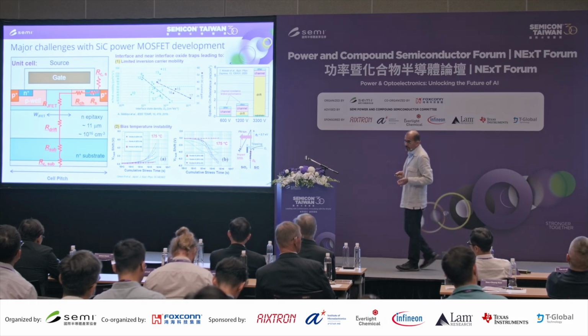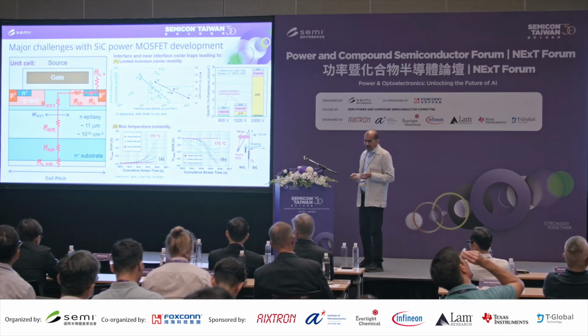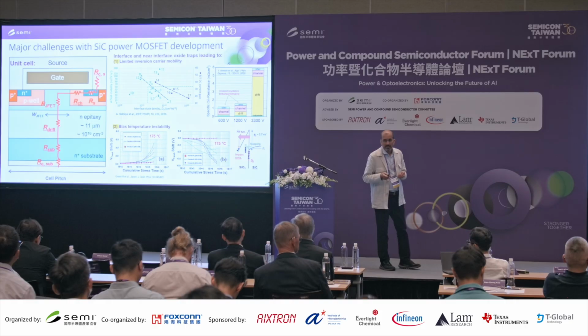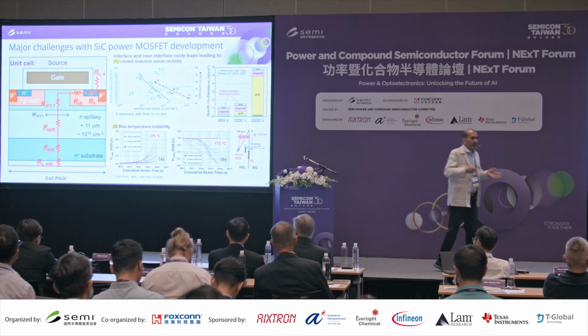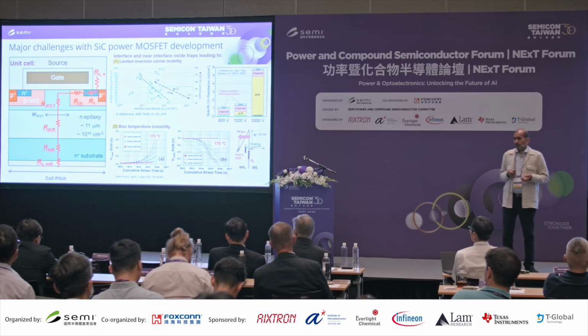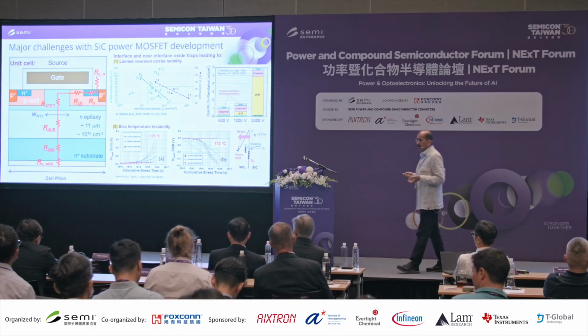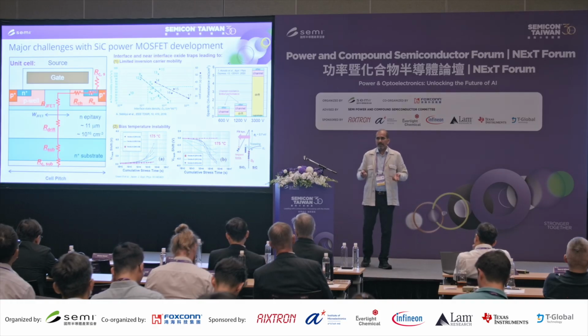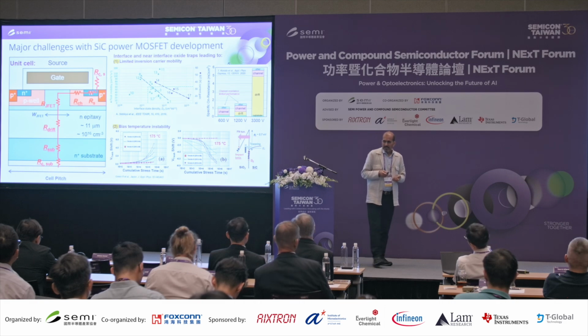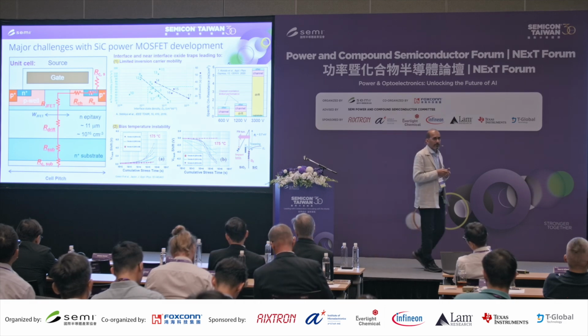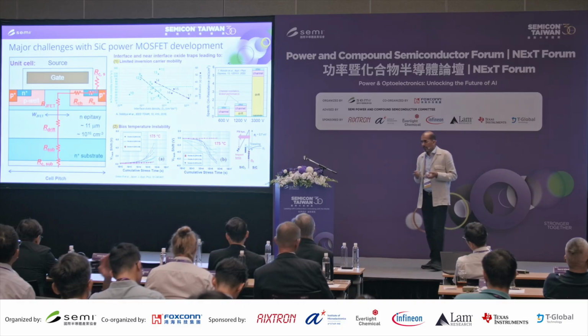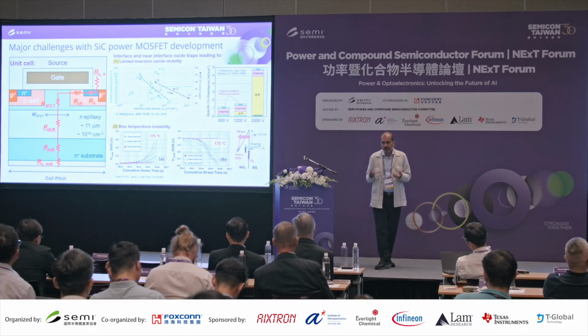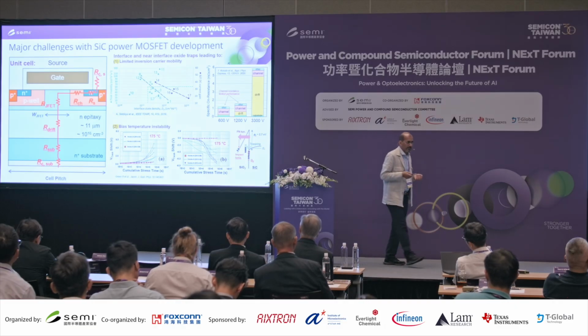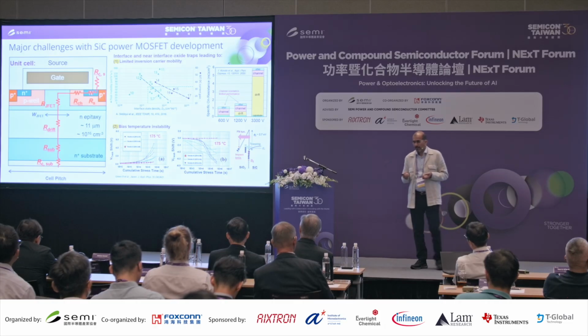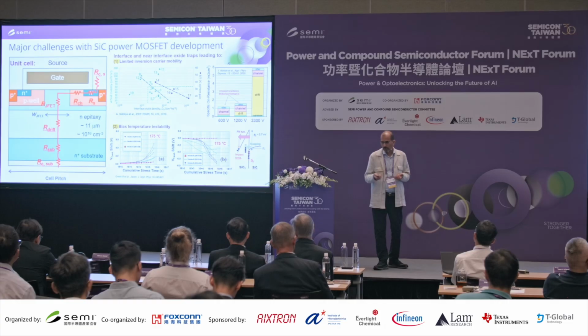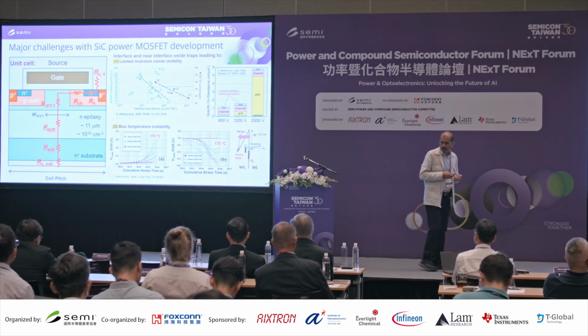So that means it requires a lot of engineering. Because of that, you can see in the right side figure the channel resistance, especially for low voltage devices, and when I say low here, it is up to 1200 volt, which is for EVs. For up to 1200 volt devices, the channel resistance is a significant part of the total resistance, and one needs to really improve that to have highly efficient power conversion. Another issue is the bias temperature instability, the threshold voltage shift. When people solve this interface problem by NO POA, N2O POA, there is damage in the oxide. That damage generates traps, and those traps capture carriers and thus shift the threshold voltage, as explained by Agarwal et al. in the bottom graph.